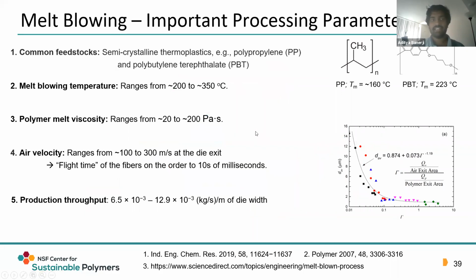Some common feedstocks, like in the case of N95 masks, are polypropylene and polybutylene terephthalate, which provide a high melting temperature, giving the upper ceiling temperature up to which that particular polymer fiber is stable. Typical melt blowing temperatures range from about 200 to 350 Celsius, while viscosity ranges about 20 to 200 Pascal seconds for optimum performance. As shown in the fifth bullet point, it's a high throughput method, leading to large scale production of polymer fibers in industry.